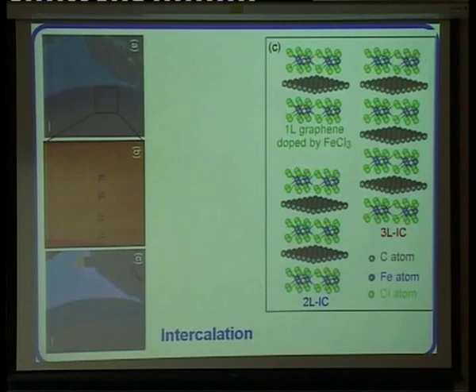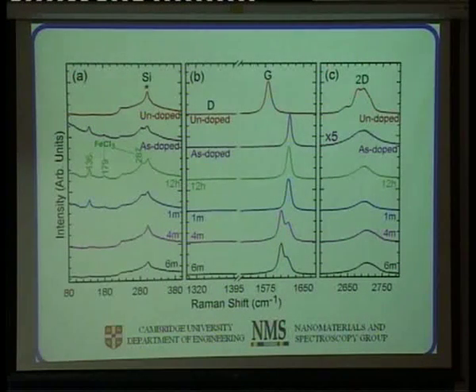So the next step to get very high doping is to do intercalation, for example with iron chloride in this case, and intercalation compounds have been known for many, many years. If you put the intercalant in the middle, you can decouple the individual layers as well as getting a very high doping level. So this is an undoped sample, for example, a bilayer. Once you put the intercalant, the 2D peak starts behaving as in the case of a monolayer, because the intercalant is shifting one layer from the other, and so the bands are not interacting anymore, or not so strongly, and so essentially they start behaving as individual monolayers.